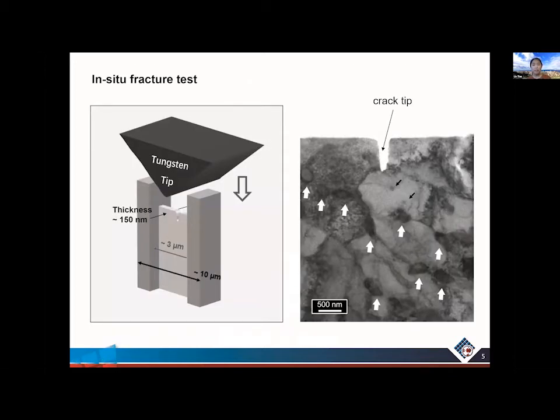For making the in situ fracture test, we cut the sample using focused ion beam. First, we cut a big piece of material with the size of about 10 microns, and then further thin the center part to make it electron transparent. The thickness is about 150 nanometers. So we leave 2 big pillars outside for taking the fracture test.